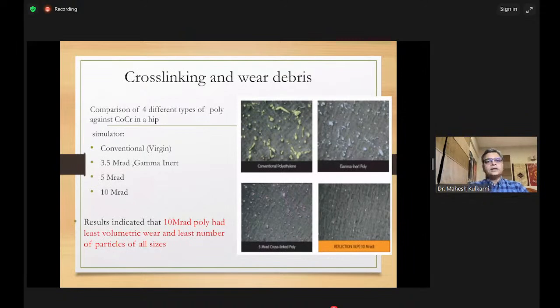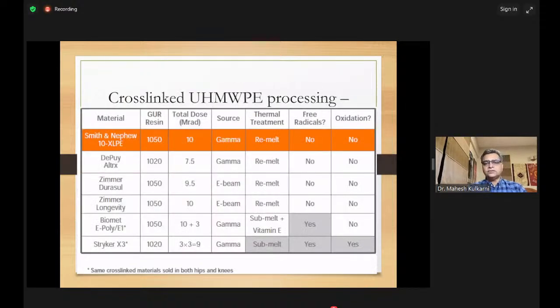So if you see cross-linking and wear debris, you see that there are 4 different types of poly against a cobalt chromium in this experiment here in a simulator, where you get a conventional polyethylene on the left-hand corner here, 3.5 megarad, 5 megarad, and 10 megarad. You see the 10 megarad polyethylene is probably the best, with the least amount of volumetric wear, as well as the least number of particles of all sizes which are present. Now, these are the graphs that all the fellows should know.